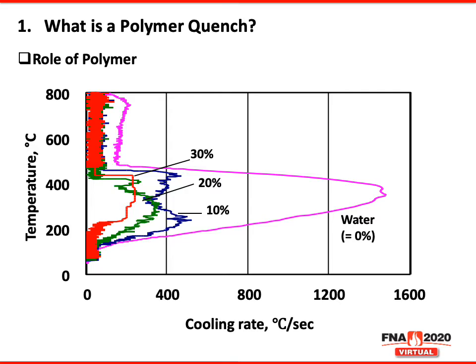Now this graph here shows the maximum cooling rate. So just plain water is somewhere around 1,500 degrees per second. You can see that that's going to be quite fast compared to a 10, 20, and 30% solution of polymer. But as I said, the higher the concentration, the slower the cooling speed, and the less likely you are to have distortion and cracking.